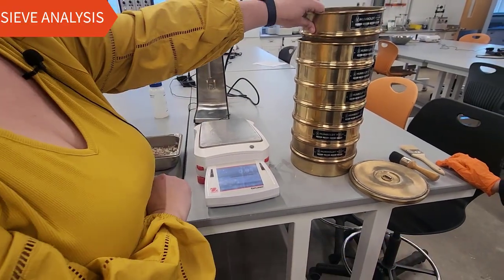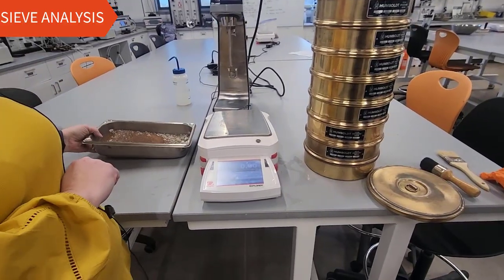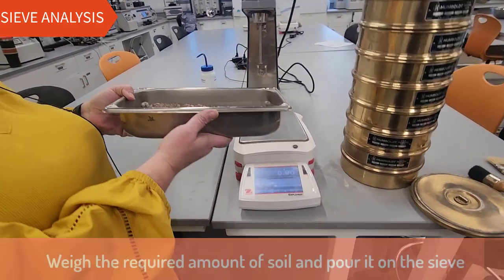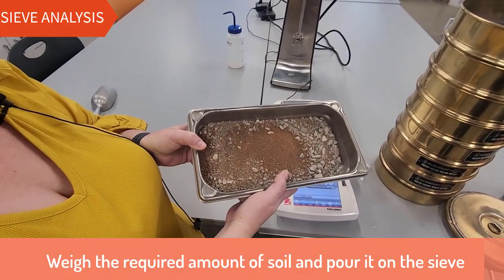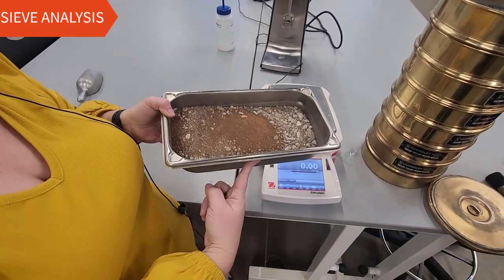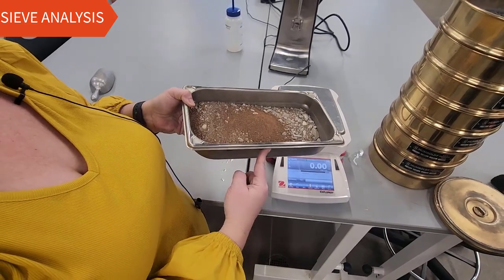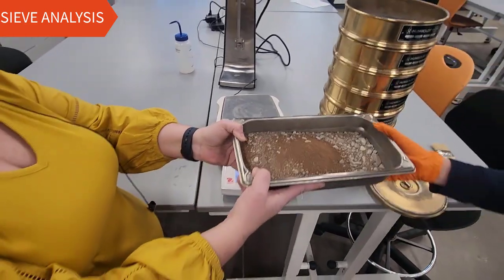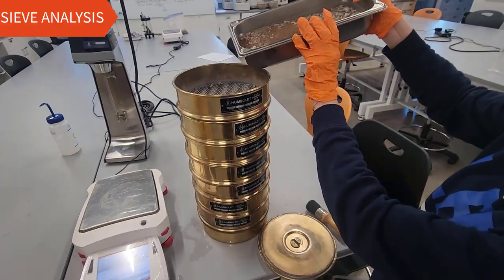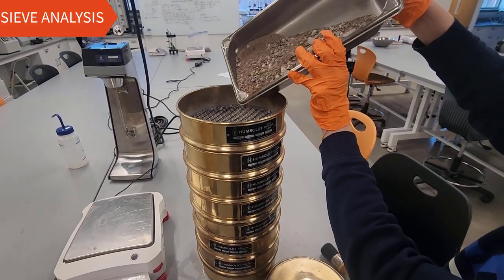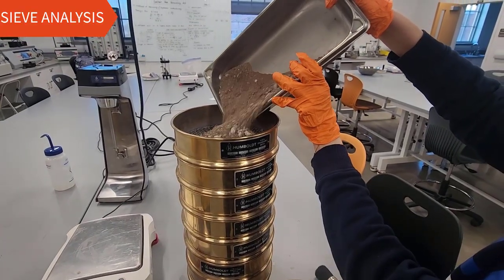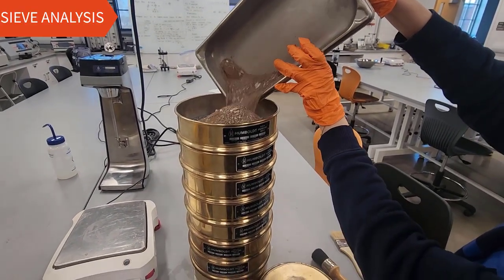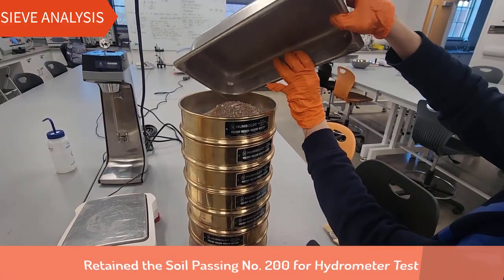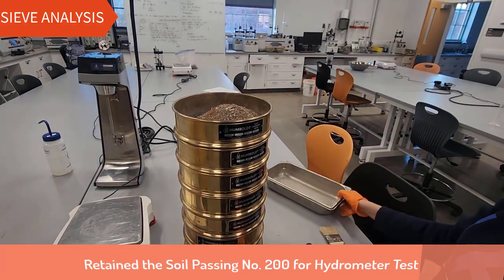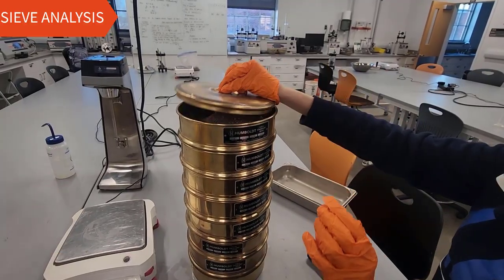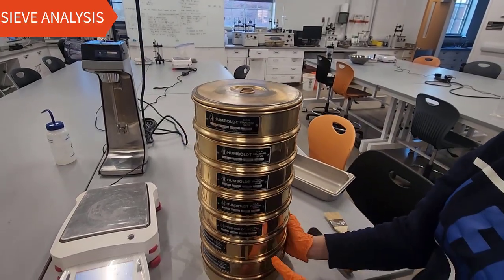Once you're done with that, your TA will have provided you with a soil sample. This soil sample we've got, we were instructed to weigh out 1,200 grams of soil. So we've got 1,200 grams of soil, and this is what we're going to sieve. Because we're going to run the hydrometer test on this soil after we've completed the sieve analysis, we're going to make sure that we retain the soil that's past the 200. So write a note on it, whatever you need to do, retain the soil passing the 200.